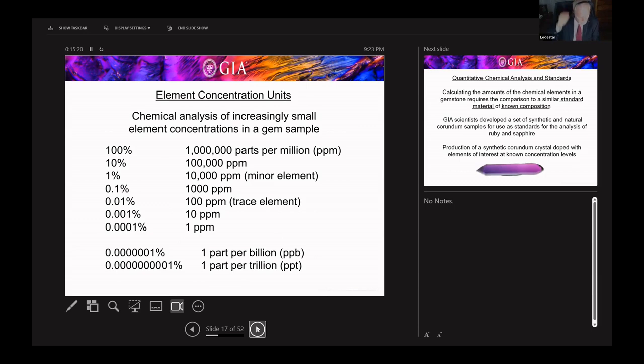Historically, mineral analyses would be reported in percent, and typically a percent is an oxide, percent iron oxide or percent magnesium oxide. But today, we oftentimes use a unit called parts per million. I just wanted to relate what a parts per million is to a percent. So just 1% is about 10,000 parts per million. 0.01% is 100 parts per million. This is the range of where trace elements and minor elements, the ones we're analyzing for, occur. And even today, we're chasing after increasingly smaller concentrations of parts per billion and maybe eventually parts per trillion. This is the world of gem testing in terms of chemistry.